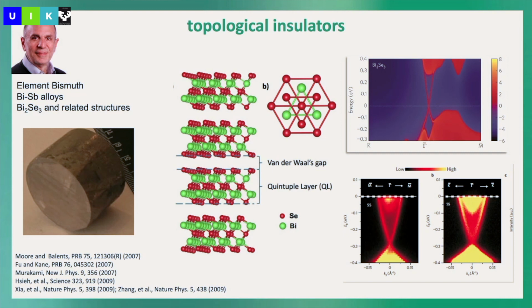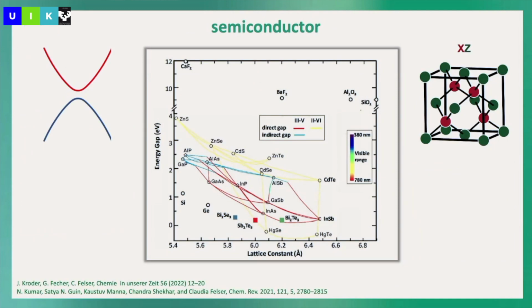And I'm 100% sure there are more hidden, really very good topological insulators in the family of oxides. But therefore, I try constantly to motivate. But most of the time, if you do the simple band structure calculation, the oxides become metallic when they are insulating. So I simply go to the database and say, oh, it's a yellow powder. So, nice prediction, but it's a yellow powder. This means it has a quite big band gap. Okay, so we have to have a better treatment of oxides. Okay, yeah, so then it was clear. So here are the candidate materials, because these are the negative band gap materials, the inverted band gaps.